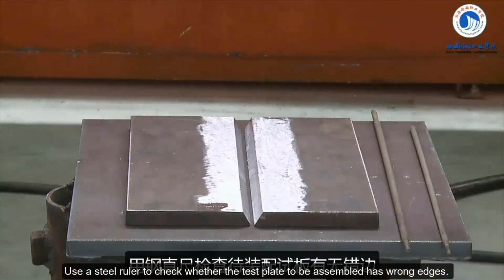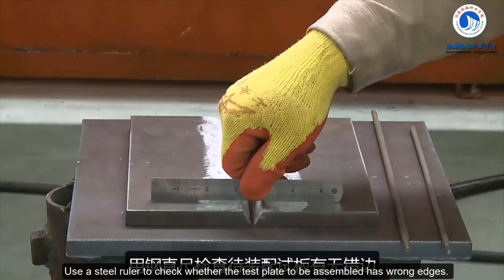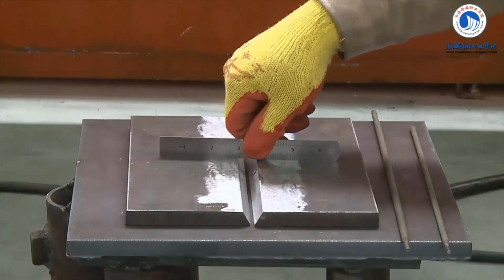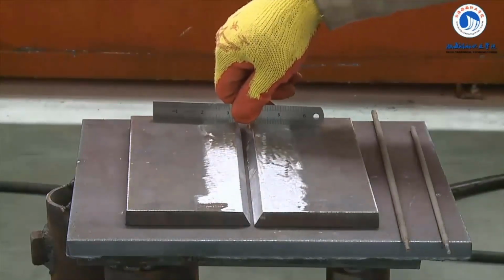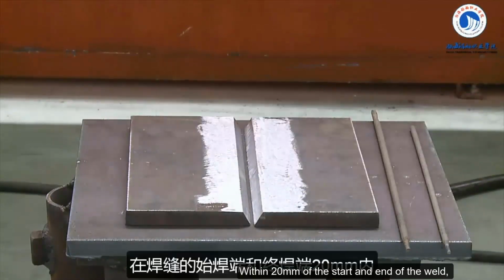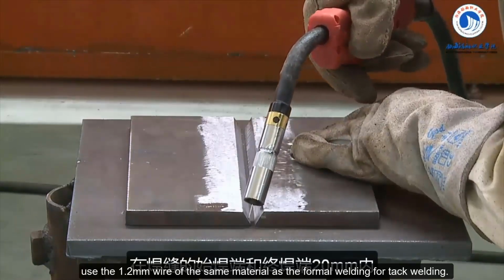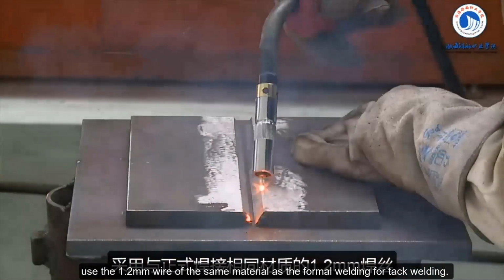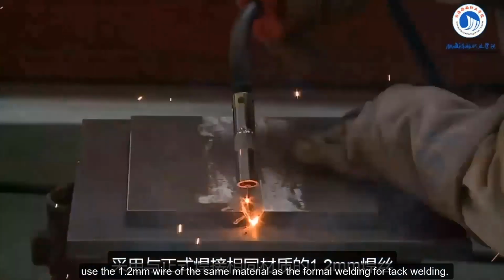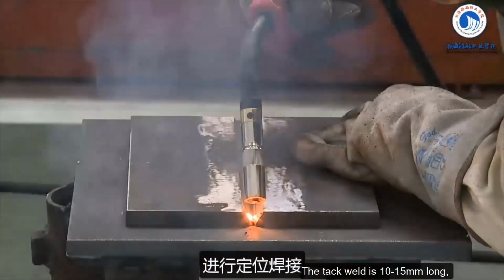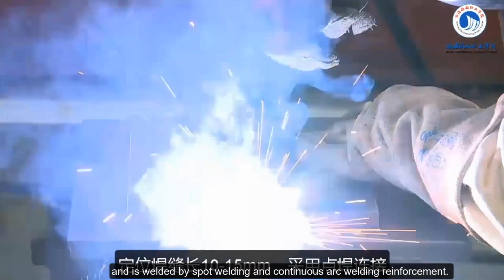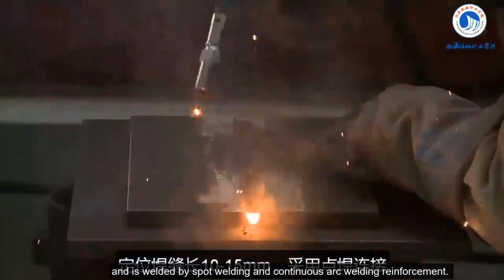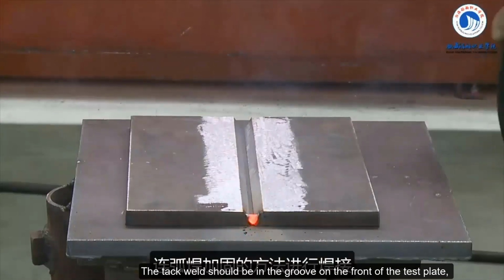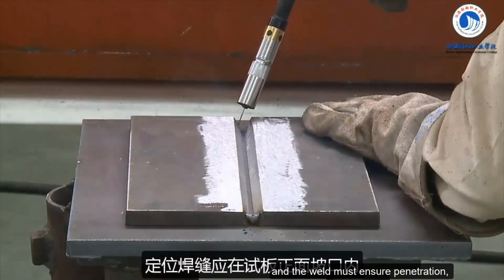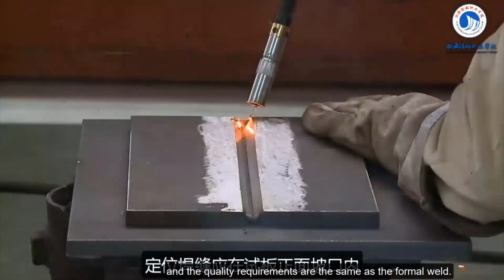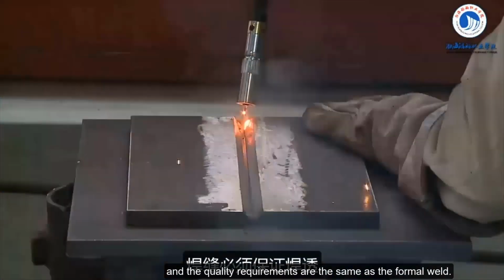Use a steel ruler to check whether the test plate to be assembled has wrong edges. Within 20 mm of the start and end of the weld, use the 1.2 mm wire of the same material as the formal welding for tack welding. The tack weld is 10 to 15 mm long, and is welded by spot welding and continuous arc welding reinforcement. The tack weld should be in the groove on the front of the test plate, and the weld must ensure penetration. And the quality requirements are the same as the formal weld.